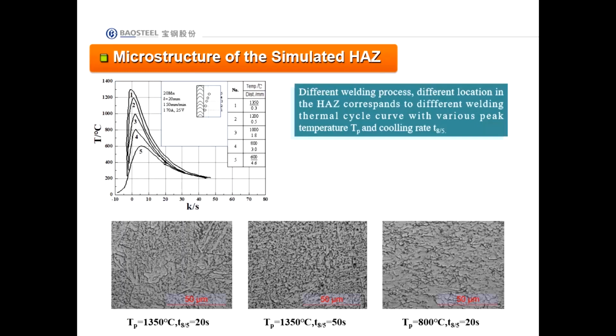the cooling rate we describe by the t8/5. It is the time to cool from 800 to 500 centigrade. The t8/5 is different: 20 seconds, 50 seconds. And we also compare when the peak temperature is 800 centigrade. The microstructure is different, and also sometimes the mechanical properties are different.